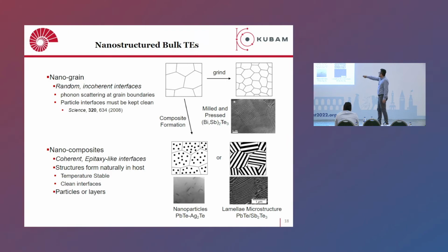So you can also, as I said, introduce some nanograins, which means, let's say this is your grain structure, you have these grain sizes, large grain size. For example, if you grind this, you can create smaller grain size, which means you introduce a lot of grain boundaries here, you increase the grain boundary density, and this is scattering more of the heat-carrying phonons and it can lower the thermal conductivity.